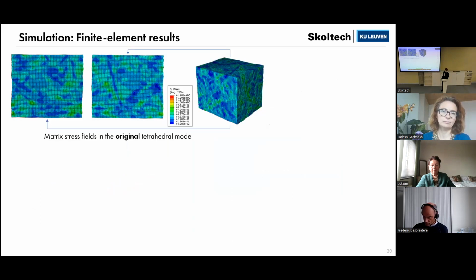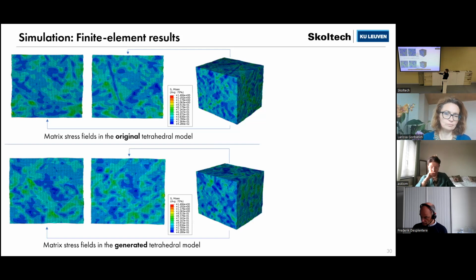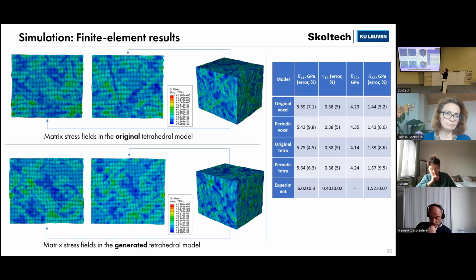Here are the results of the original tetrahedral model. When we apply periodic boundary conditions, the top and bottom slices should look quite similar, if not identical. But here we have a difference that doesn't have physical meaning, because we applied periodic boundary conditions, yet we have very large jumps. For example, here we have low stresses and here we have larger stresses, a property jump that's not physical. But when we move to the generated images, the properties on the bottom and top slices are already identical and have similar stresses.